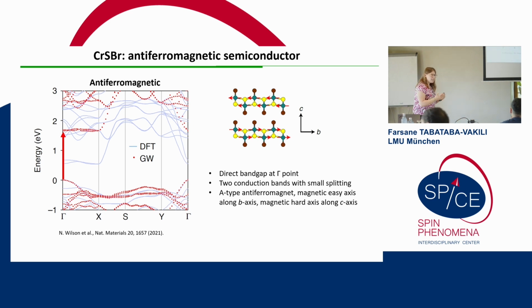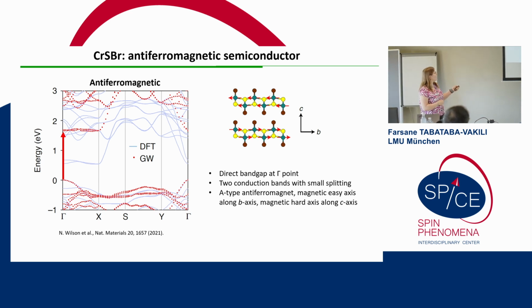So why is chromium sulfur bromide interesting? Many reasons. For me, as an optical spectroscopist, it is because it is both a direct bandgap semiconductor that hosts van der Waals excitons, as well as a layered A-type antiferromagnet. Looking at the band structure here, the red dots, the DFT plus GW, we have a direct bandgap at the gamma point, and then we have nearly flat bands along gamma-X in the conduction band and highly dispersive bands along gamma-Y. So the material is also quasi-one-dimensional. And we have two conduction bands that are very closely spaced in energy, which is going to be important later on when we look at our model.